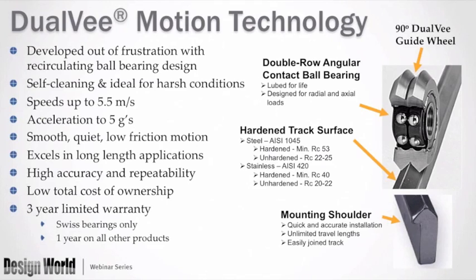In its core, it's a double row angular contact ball bearing, and it's heat treated. It's hardened up to 53 Rockwell minimum, and it's available in stainless steel and carbon steel. In the stainless steel, it's 420 stainless, available up to 40 Rockwell, so it's a little less hard there. It was developed out of frustration with recirculating ball bearing design, and the problem with those, we'll look at in a second, is that the balls themselves can attract debris, leading to failure.